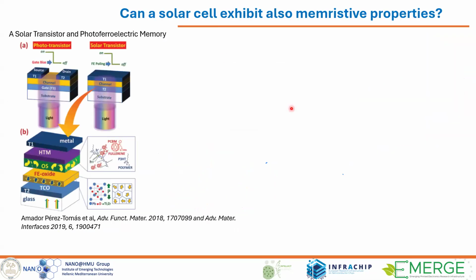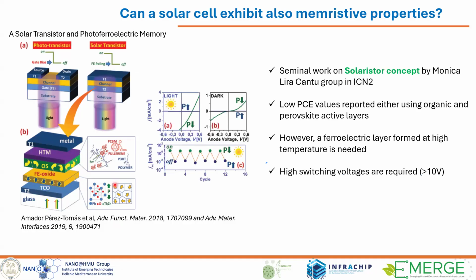So before we continue, the question here is, can a solar cell also be at the same time a memristive device? This started a few years ago by Professor Lira Cantu's group in ICN2 in Spain. They demonstrated a solar transistor, as they call it. Actually, it was an OPV, an organic solar cell with a ferroelectric layer integrated, and they have shown that they can control the current through the device, of course by light, but also by changing the polarization of the ferroelectric material. So it was like a solar cell that can also be a type of memristor, or solaristor, as they named this device a few years ago.